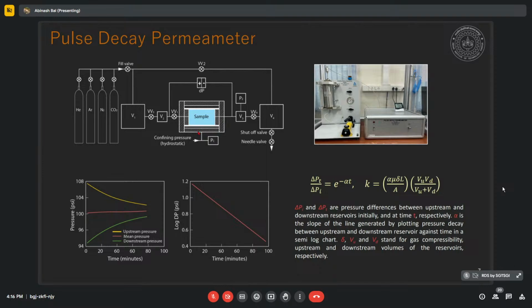Suppose we collect the samples from 2 kilometer depth, we apply the corresponding confining pressure here. Then using different gases, suppose we want to measure the apparent permeability using nitrogen gas, then we inject a certain amount of pore pressure in both the upstream and downstream reservoirs. That means V1 and V2 is the upstream reservoir, V3 and V4 is the downstream reservoir. So let's say we apply 105 psi, I'm just giving a hypothetical value. Then we apply 105 psi in both upstream and downstream, and we wait for equilibrium in both.